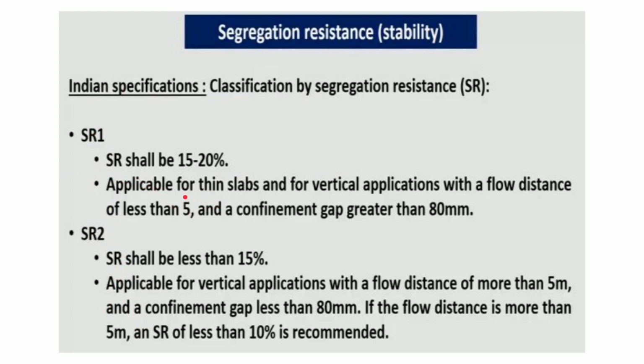So if we need this one, if it is used for thin slabs and for vertical applications with a flow distance of less than 5 meter, and a confinement gap greater than 80 mm, then it is allowed to have segregation resistance of 15 to 20%. So for thin slabs, vertical application, having flow distance of less than 5 meter and confinement greater than 80 mm, we are allowed to have an SR value of 15 to 20%.